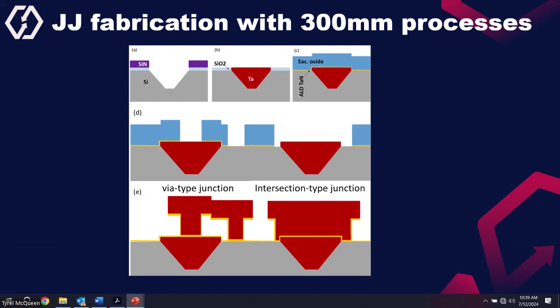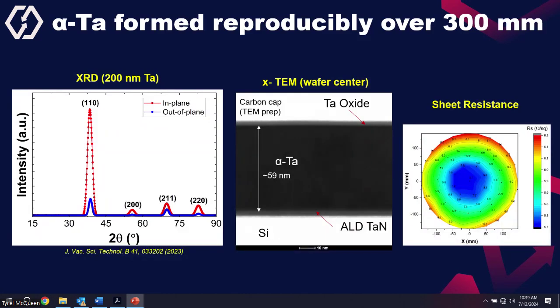When we develop a new technology, first we need to establish different elements of it, and that is what we did, and I will take you through the different steps. This is the fabrication flow, the different steps that we have to take. But before starting the fabrication, what do we need to make sure? First, whether we can get repeatable alpha tantalum phase across the entire wafer with good uniformity in terms of thickness and sheet resistance, and whether we can get alpha tantalum every time, whether I deposit it today or 1 year later. The alpha phase is important for quantum applications because its Tc is high and for some other reasons. Using XRD and sheet resistance measurements, we confirmed that we are getting alpha tantalum every time.